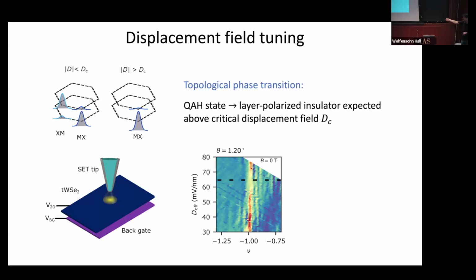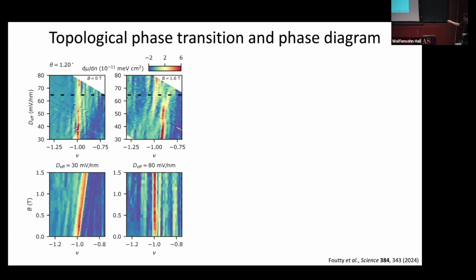And this is a capacitive sensor. So you're integrating with some areal average signal from everywhere that's capacitively coupled, with some appropriate weighting by 1/d. And eventually, if we go too far, then everything smears out so much that we have no hope of actually seeing it. So it's not a question of breakdown. It's a question of how homogeneously we can actually do this and get sensible data out. It's actually nice that there's a topological transition. Sloped versus not sloped is a really crisp distinction that makes it easier to tell what's going on.